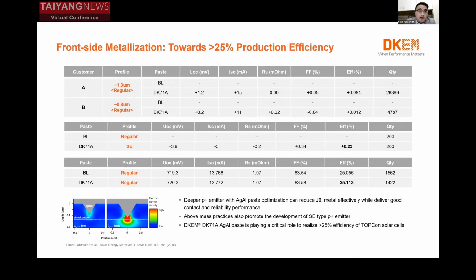On this page, we try to show some results. We work with different customers in the industry. First one, we learned that with the deep junction, our paste can indeed show higher VOC and higher fill factor, eventually a better efficiency benefit. You can see the data with 1.3 micron deep junction. The efficiency benefit is much better than the shallow junction.